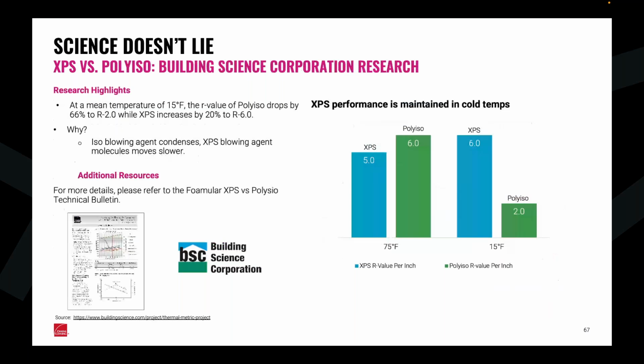The next one would be a polyisocyanurate material. These materials actually may start out with having what would be perceived as a higher R value. The Federal Trade Commission requires that we report that R value at a 75-degree mean temperature. But one of the things that gets brought up is that in a colder temperature, so in a colder climate when you need some of that insulation, the R value can actually begin to drop. So that's one of the reasons why XPS may be selected in some of these colder climates, because we're actually seeing a slight increase in the R value of the material itself.